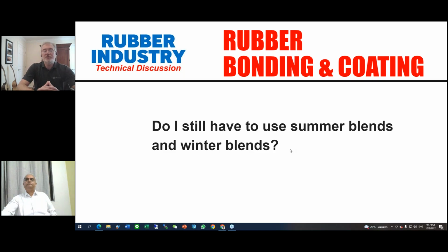And so the beauty of this, when you add temperature and viscosity control, you no longer have to have summer and winter blends. And the question is, when do I switch from my summer to my winter blend? And when do I switch back? I get crossover days in the spring and in the fall when neither one is really perfect. And so how do I handle those? And the answer is, with temperature and viscosity control added to your automation, you don't have to choose. You always use the same formulation, the optimal formulation, and you bring it to the same temperature independent of changes from season to season. That's a very important point.